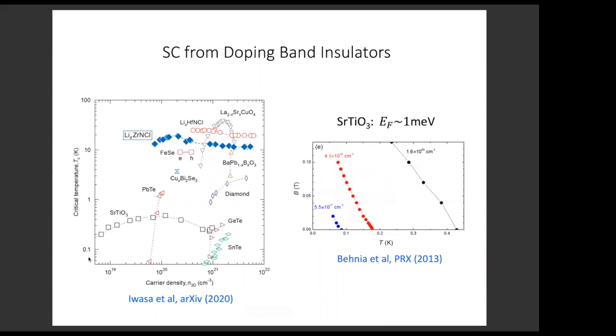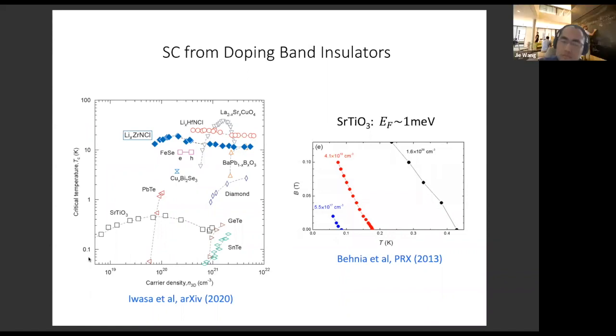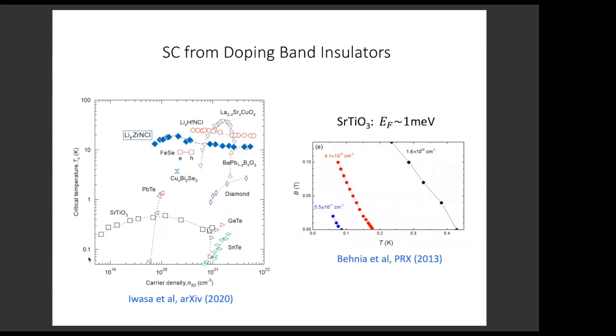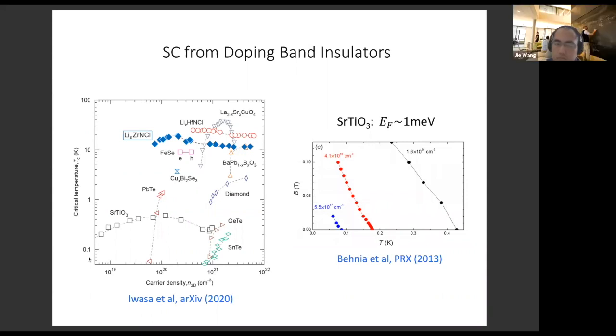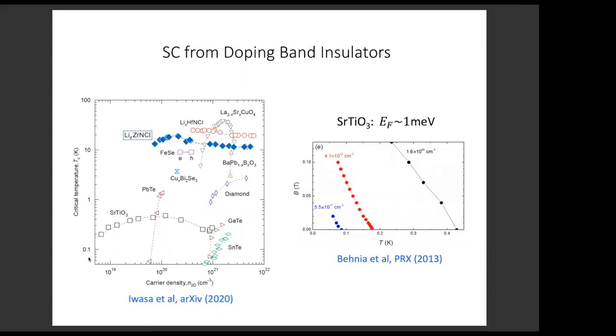So I'm not going to discuss the Mott problem here, but on the other hand, there's also a lot of interesting experiments showing superconductivity arises by doping a band insulator. For example, here in this phase diagram, you can see a lot of materials like strontium titanate. It's a classic example. It has a large gap band insulator, but very small amount of doping gives rise to superconductivity with a very large Tc over TF ratio.